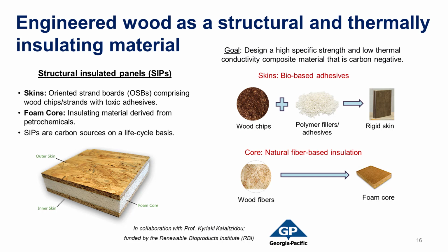And so the way we do this is we have these waste wood chips. We add bio-based polymers as our adhesive rather than carcinogenic formaldehyde-based adhesives. And then we can hot press to form this rigid skin. So that's the top and bottom layer. And for the core, instead of working with styrofoam and other petroleum-based foam cores, we're actually working with natural fibers. So we work with wood fibers, which we can compress into these foam cores, and it can have comparable thermal insulation properties as the styrofoam.